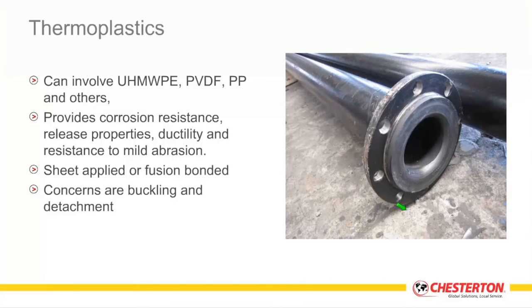These can provide extremely good resistance, and they can be used to line mild steel pipe. They provide great corrosion resistance, fantastic release properties. They can have good ductility and resistance to mild abrasion. Normally, these materials are applied in a sheet which is glued on or thermally attached to the material by fusion. But some of the concerns that we have with these materials is the ability for them to withstand force and resist disbondment and detaching, because when these materials detach, they tend to detach catastrophically, and that can result in downstream pluggages of your process flow.